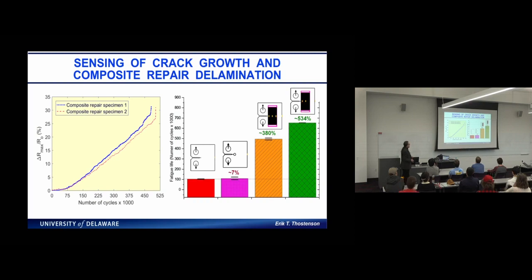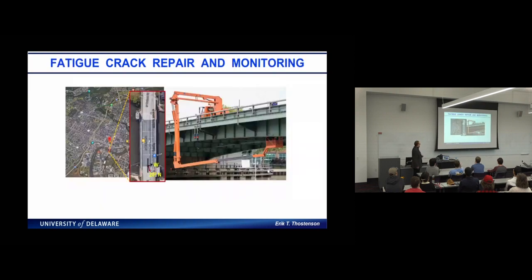This is the fatigue life. This is where we drilled a crack stop hole. Only increased it less than 10%, right, in terms of fatigue life. But when we add our composite repair, we're getting around 400% change. So a very significant change in the fatigue life. And this was where it was fun. I got to be a civil engineer for a day. So we went out on the bridge and actually installed this sensor.